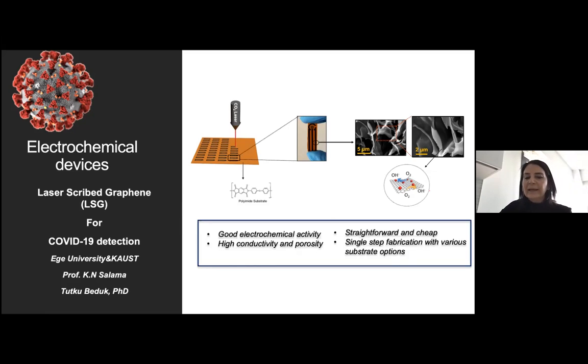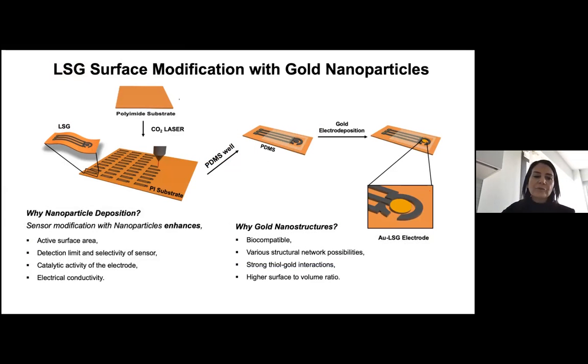LSG electrodes have good electrochemical activity, and are straightforward and cheap. It is possible to obtain a higher number of electrodes at the same time with high conductivity and porosity, very proper for further modification or one-step surface modifications. After preparation on the polyimide substrate, gold nanoparticles are electrodeposited on the surface. We prefer to use this kind of surface. As we all know, gold nanoparticles provide higher surface area and are also compatible with biomolecules.